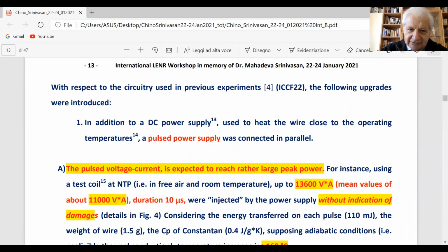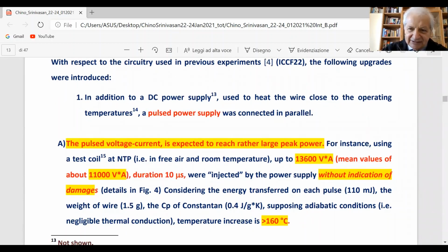The procedure to get the high temperature is to give a DC current to preheat the wire, typically 500, 600 degrees, and then give the strong pulse in a short time, typically 10 microseconds. So the temperature increases from, for example, 600 static up to 700, 800 degrees. The power injected is very large. In some tests, we reached up to 13,600 watts, with a mean value of 11,000 watts, duration 10 microseconds. These tests are made at room temperature, and up to now we have no degradation of the wires. So the Constantan is a very harsh material.